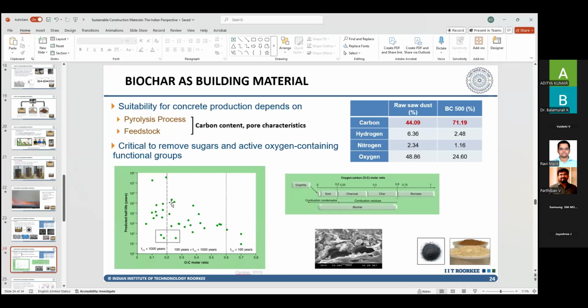Furthermore, the temperature at which you heat the biochar, and the speed at which you reach that temperature, these two things control the amount of pores and the type of pores that are generated in the biochar. This is important because if you want to use the biochar for internal curing, you want a specific size of pores to be available, no larger than that, no smaller than that. Smaller pores will not be able to hold water effectively, and larger pores will create voids inside the concrete that, instead of providing internal curing, will act as weak zones.